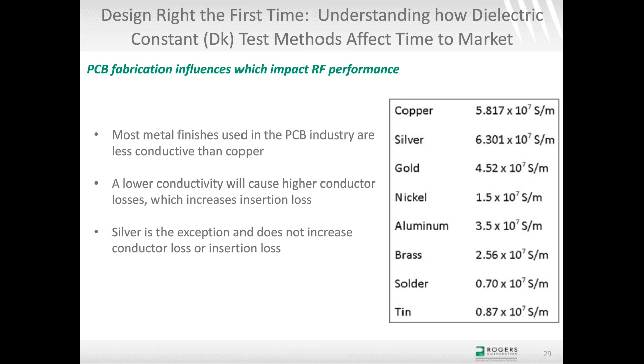And these different metals typically have lower conductivity than the copper, which translates to having worse conductor losses, and that's going to affect the insertion loss. So worse conductor loss means worse insertion loss. The exception would be silver. There is an immersion silver process used to make printed circuit boards, and that silver is definitely more conductive than copper, which is a good thing, but it's also applied so extremely thin that the benefit of the higher conductivity silver is probably not going to be realized until you get to very high frequencies where the skin depth is thin enough that it's using mostly the silver.